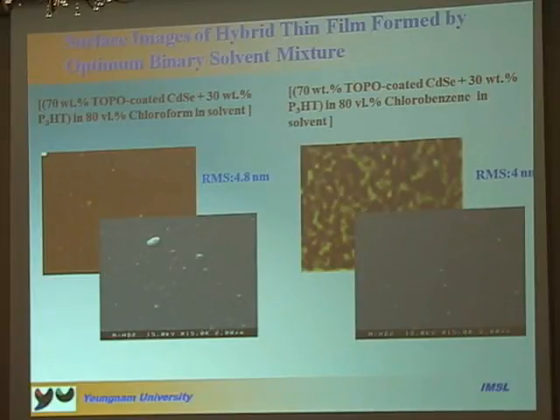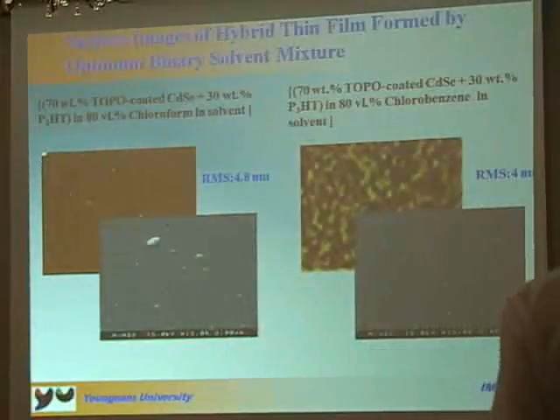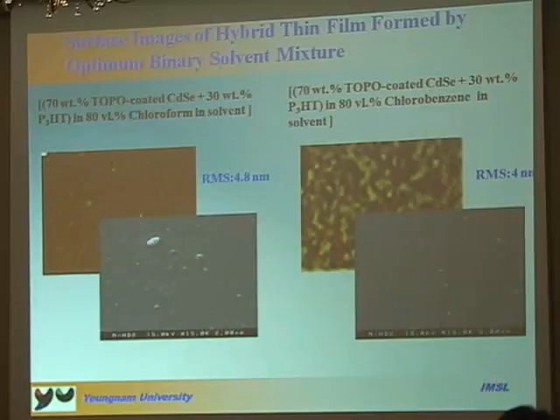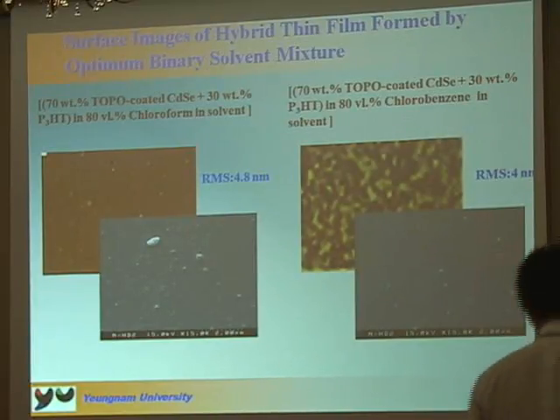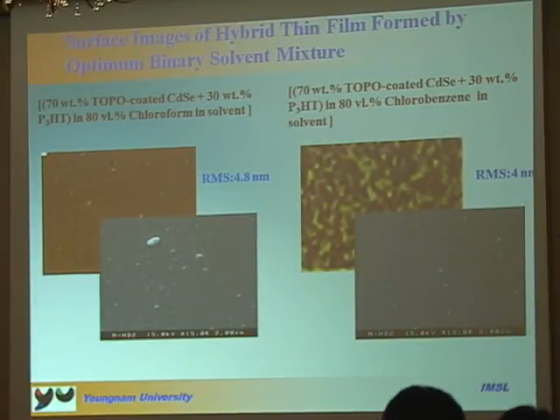Nowadays many people use a single solvent to make a composite solution, but in our experiment we try to mix two solvents, a binary solvent. In this case we use chloroform and chlorobenzene with pyridine. The morphology and the surface were investigated by AFM and SEM. We have very nice morphology and a very nice surface.